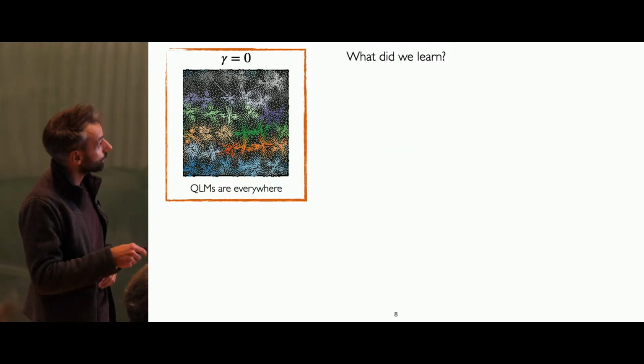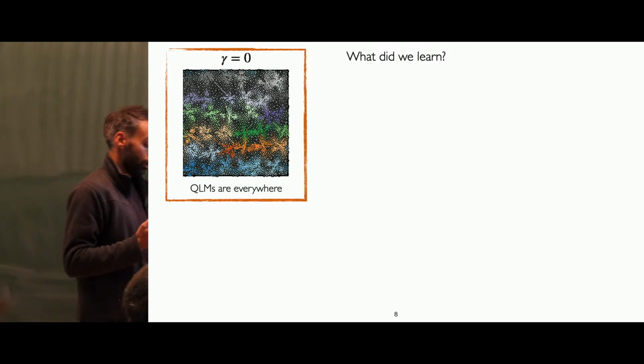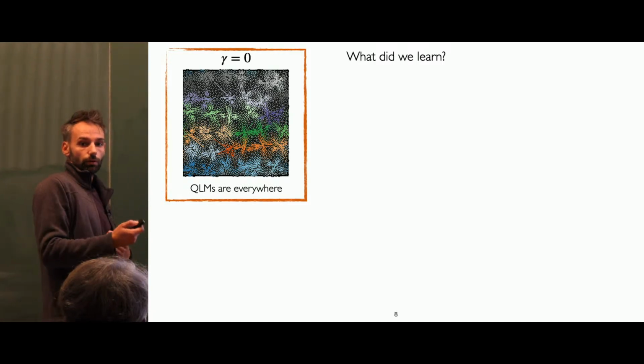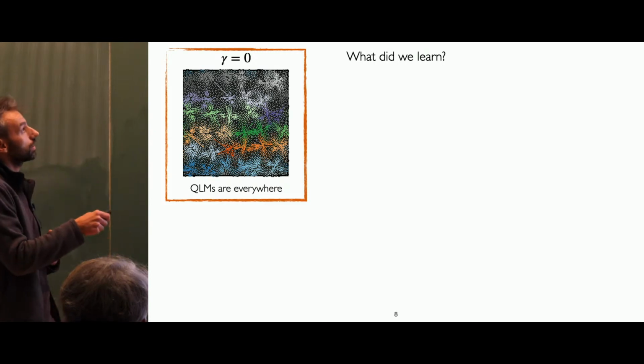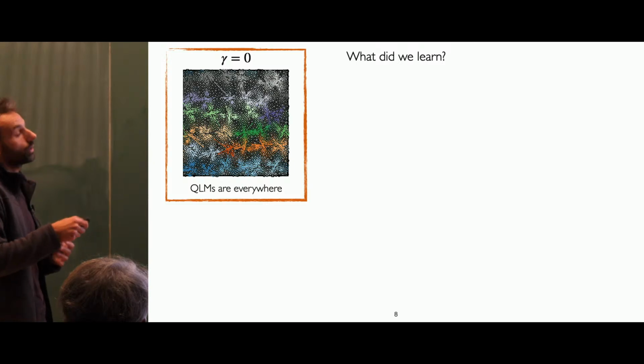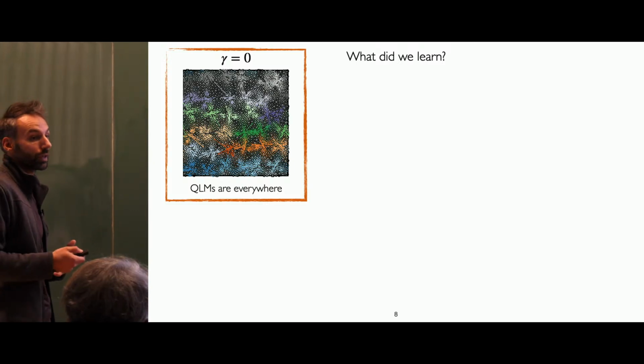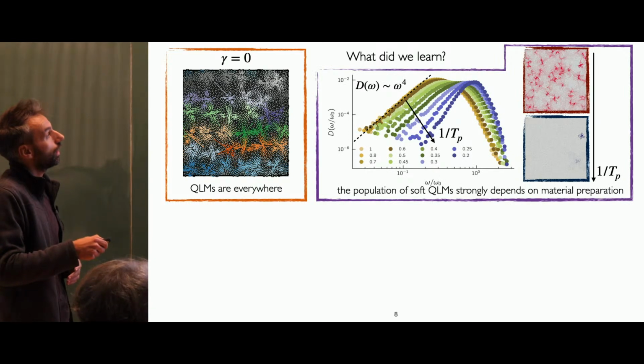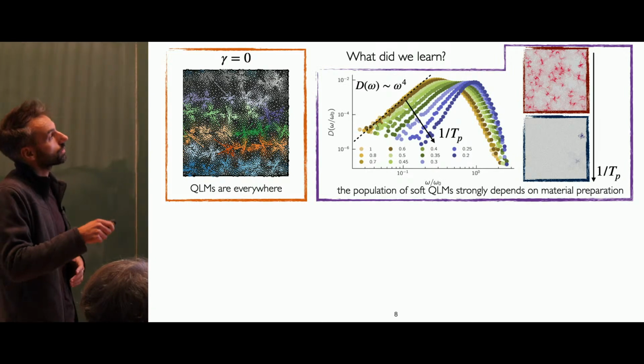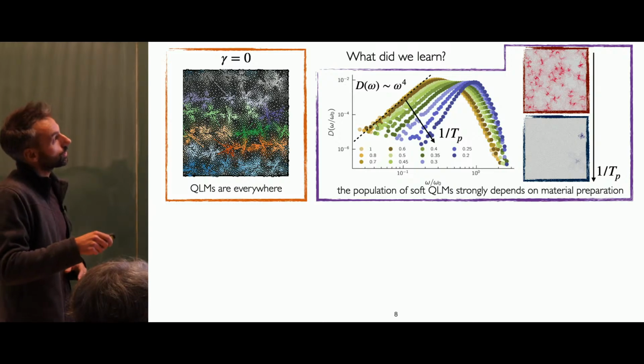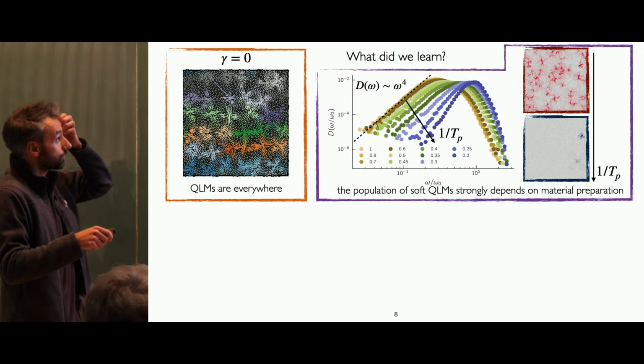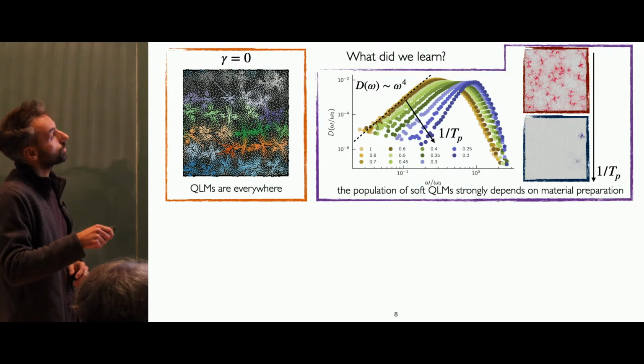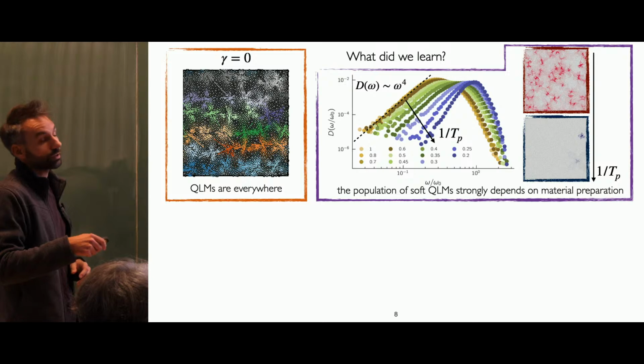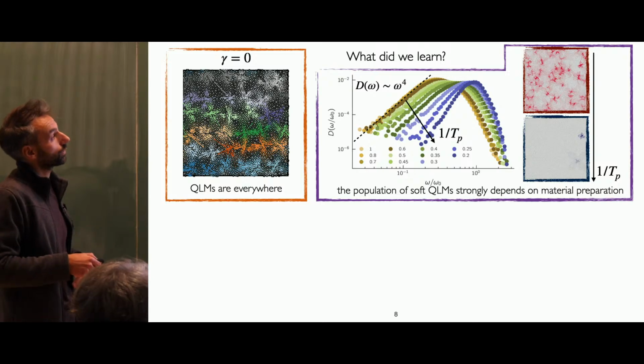So one thing that we learned is that those modes are not only there when the system is unstable at the onset of a plastic instability, but they're actually everywhere in the system. But some modes might be soft and some modes might be very stiff, where you will not see any rearrangement. So if you look at how they are distributed in frequency, so it's the density of states of my local modes in a glass, you see that indeed the majority will be strong, but you can have anomalous regions in the system where you have really a soft mode that extends towards low frequency.